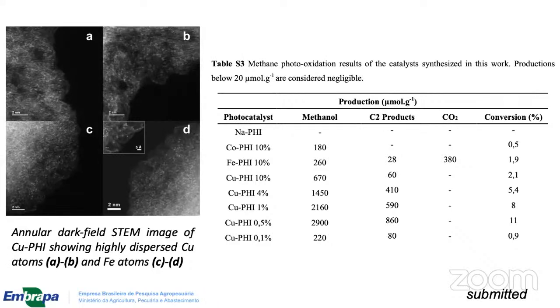But it's more interesting to see in this research that we got this with copper, while with iron, which was the system that got better conditions in the other research, we had a complete oxidation, going more to CO2 instead of methanol.